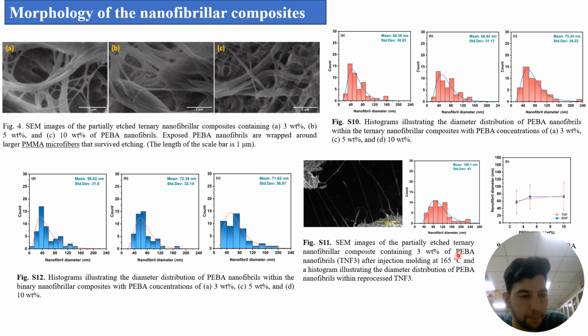In figure S12, the histogram depicts the diameter distribution of PEBA nanofiber within the binary nanofibril composite, while figure S10 I take from the previous slide because it explains it here. Comparing the average nanofiber diameter in the ternary and binary nanofiber composites, no statistically significant changes were observed. You can see here it is almost the same, so no big changes observed.